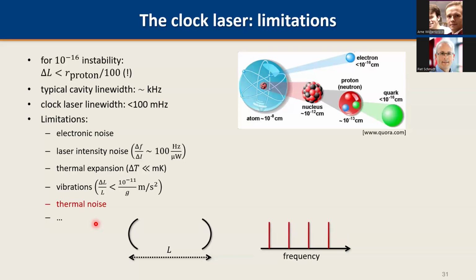It's typically amorphous coatings, and they have a very large motion given a certain temperature. But do you know how much it is, in proton radius? It's pretty much this value, like proton radius over 100. But that's also ridiculously small. Well, it averages out, because you're probing many of them, 10 to the 23 or so, and you find the average of those. Individually, they are moving. I have no idea how large the individual movement is. I'm sure some solid state physicists can tell you.